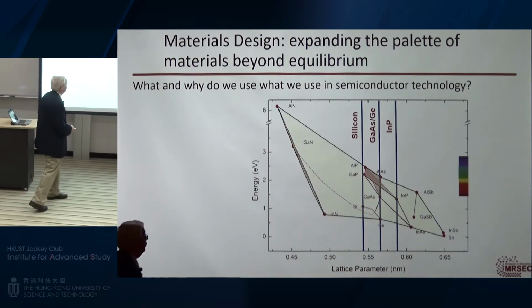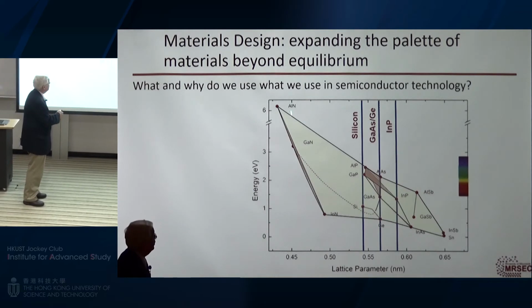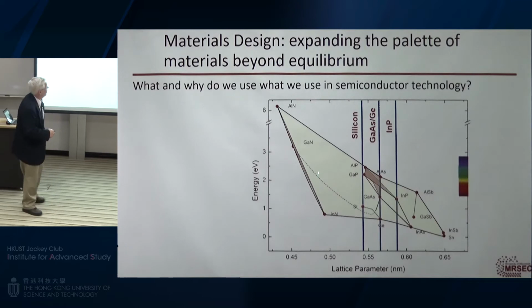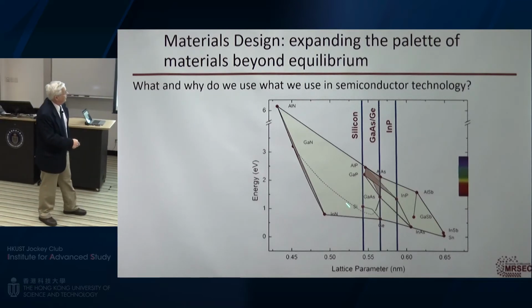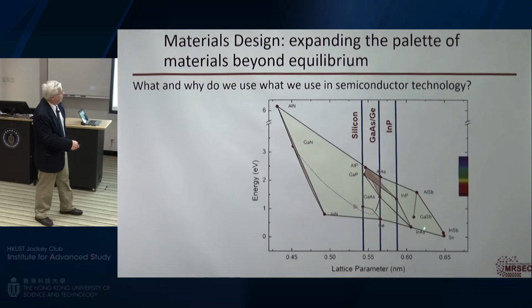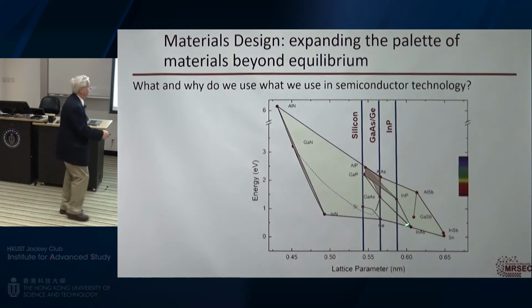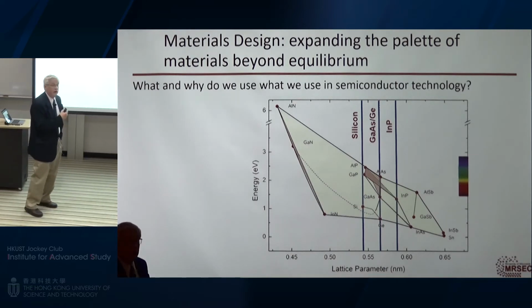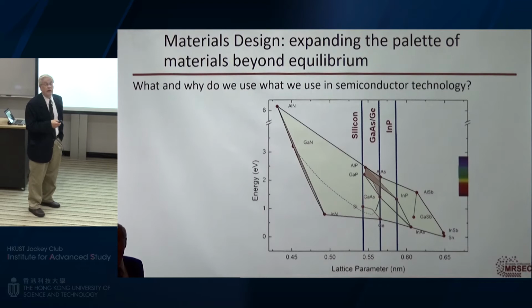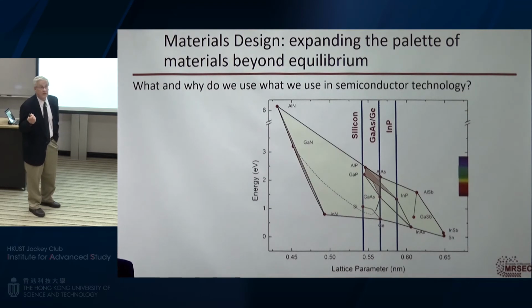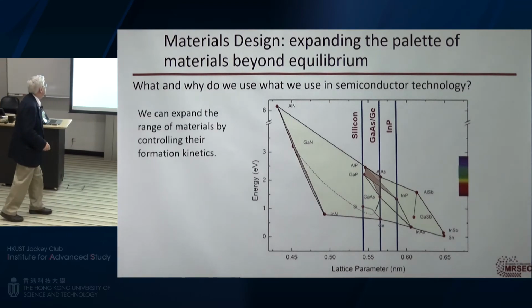So one way of looking at this is that this actually is a huge compositional space. And so one thing I'd like to do is say, I could compute an arbitrary combination of indium, gallium, for example, indium, gallium, and aluminum, arsenic, nitrogen, arsenic, phosphorus, antimony, and find a composition somewhere in this compositional region, and it could have an interesting property. And the question is, if I wanted that, could I make it? And the answer generally is no.